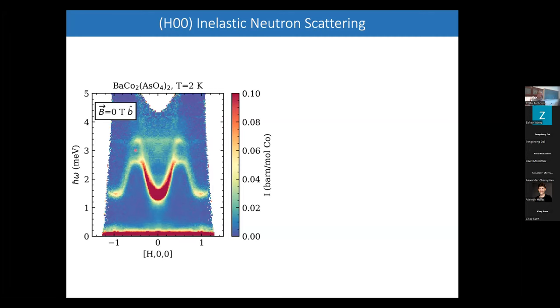We simply have this excitation spectrum, which looks a bit like what you'd expect for a ferromagnet, if you will. But there are other things that I think indicate the complexity of this system. One thing is that there's a gap in the excitation spectrum that indicates the orbital contribution to the moment, which makes it anisotropic and gives a gap in the excitation spectrum. And also you see various other features like these extra copies of things and also a continuum of scattering. And all of that is real stuff that's in the dynamic correlation function of the system and basically shows us that there is something more complex going on in this material.